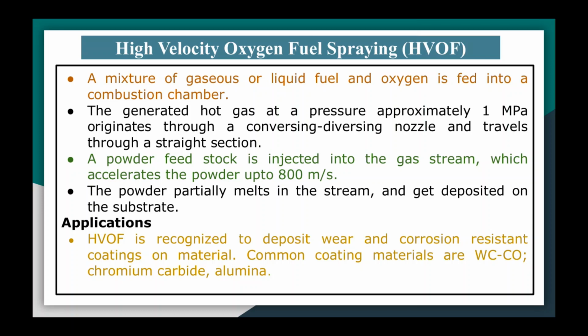The resulting coating in this way has a low porosity and high bond strength. Okay, this is the main point. HVOF has some applications. It is recognized to deposit wear and corrosion resistant coating on the material. Again, commonly coating materials like tungsten carbide, cobalt, chromium carbide, alumina, these are the common coating materials. It is used to deposit coatings of required property on inserted tool bits.